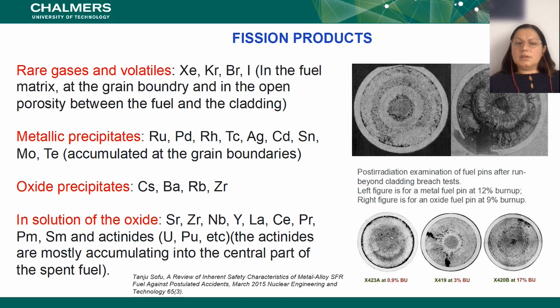So you can see very well that first you have the rare gases and the volatiles forming on the outside part, so they are migrating towards the outer part of the fuel, and then you have the metallic precipitates. You see that you have ruthenium, palladium, and so forth. So you have all these forming precipitates, which is the next part on the outer sphere. Then you have the oxide precipitates, which are getting quite close towards the middle part. And then you can also have a solution of the oxides, which, depending on the temperature, of course, can have different phases formed. And towards the middle, you have the higher actinides.